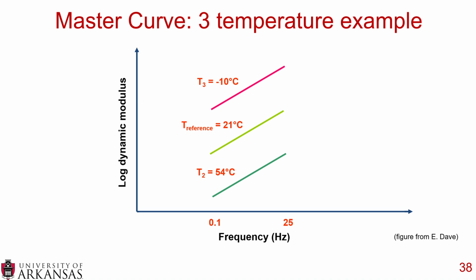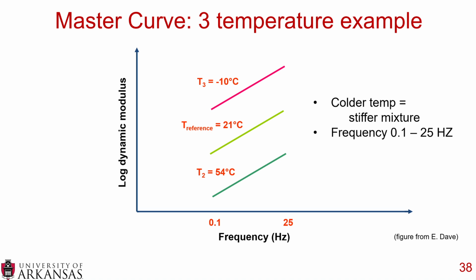So here, our equipment is constrained by 0.1 to 25 Hertz, and all we can do is change the temperature, from negative 10 up to positive 54. And what's happening here is you can see that the colder temperatures, the ones on top, are a stiffer mixture. And we can measure that stiffness at these three different temperatures from the frequency of 0.1 to 25 Hertz.